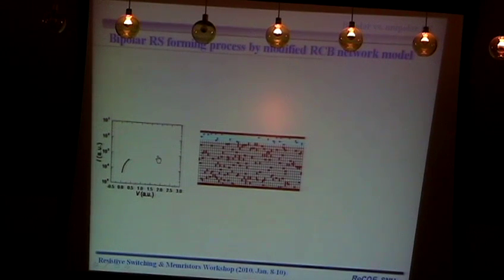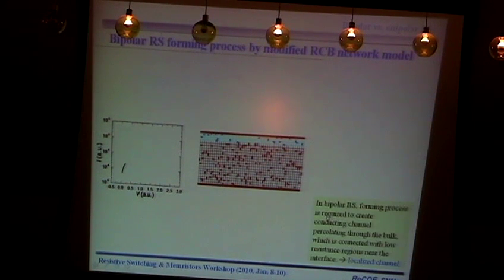So we increase the power voltages. So initially, with some kind of defect or lighting existing in the system, initially there's nothing happen. But you can see that at certain voltages at the surfaces, it will be entered to the lower resistance state. Then you can see that throughout the bulk, you can have a percolating, very low resistance state. So this all indicate that in the bipolar resistance switching, many people are using this forming process, but forming state is required because to create the conducting channel throughout the sample, because that will actually provide the main supply of the current to the system. That's the reason you need a forming process in the bipolar switching.